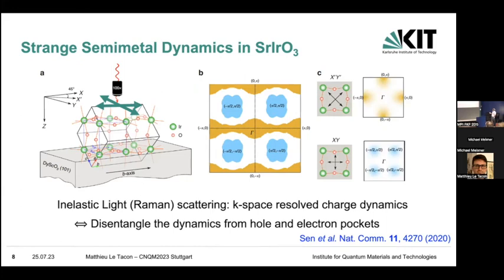But now, if you look at the electronic structure calculated by Rolf here, so that's the Fermi surface of the strontium iridate, you see that there are some large open electron and hole pockets here, and the small electron pocket here at the pi over 2 points. And using the selection rules of Raman scattering, by carefully choosing the orientation of your polarization, you can probe the dynamics of the charge either at these points of the reciprocal space, which is mostly going to probe the dynamics of the holes, or along the diagonal here, which is mostly going to probe the dynamics of the electrons. So we thought we'd give it a try.